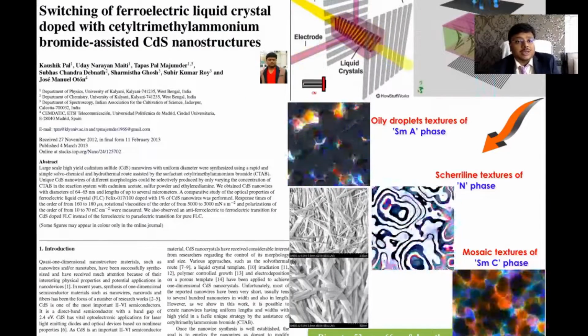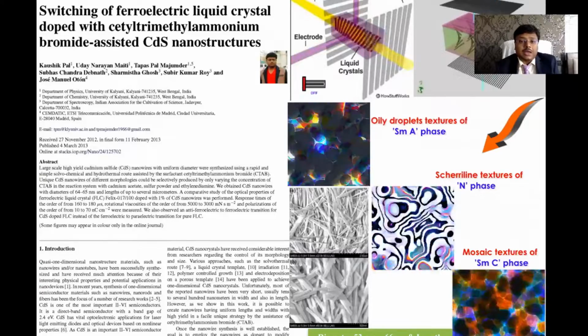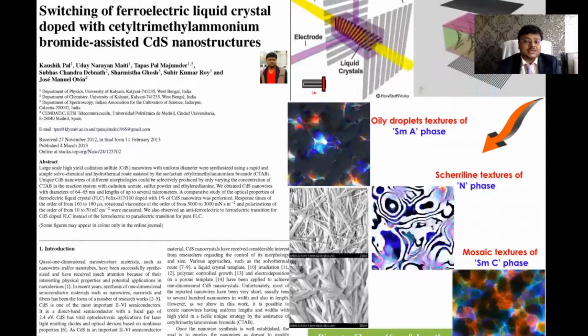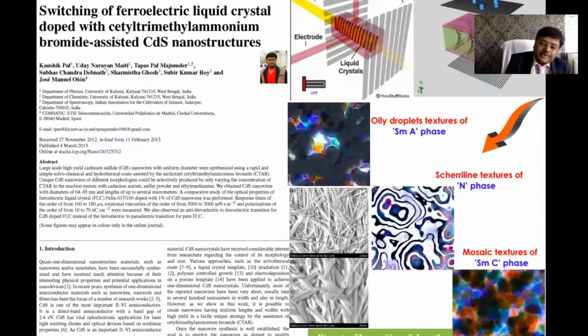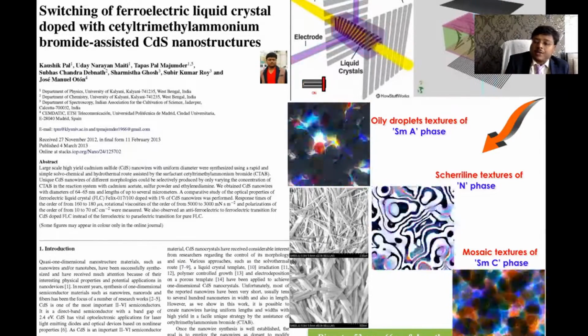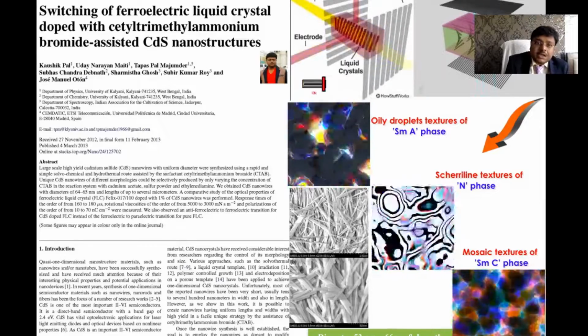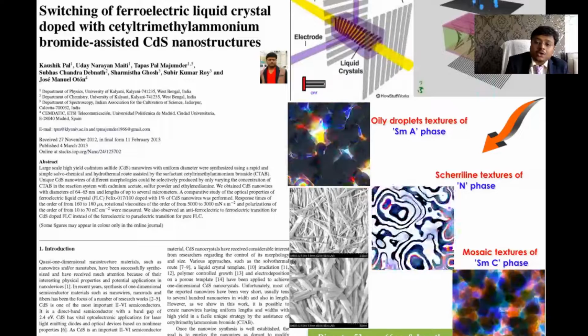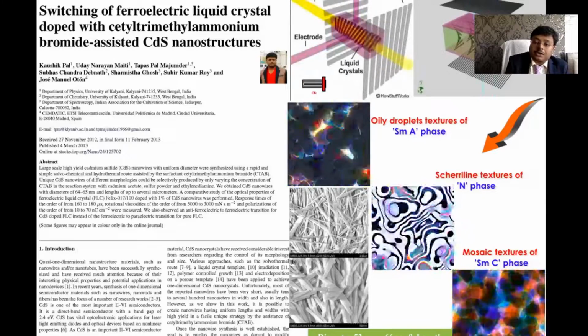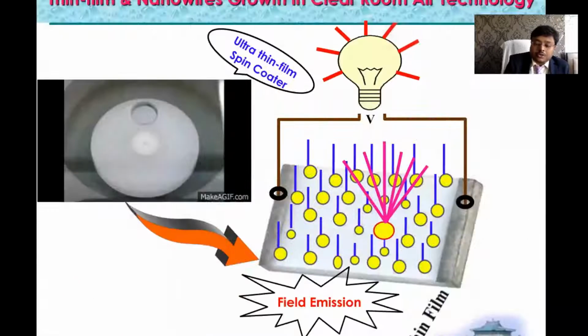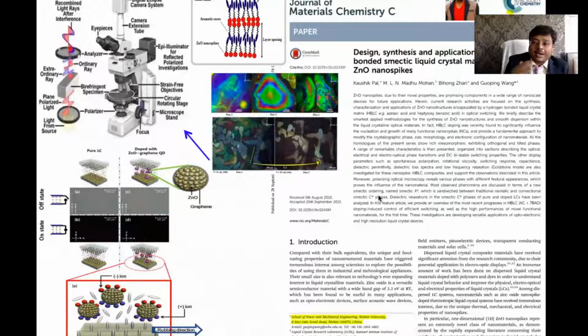Switching of ferroelectric liquid crystal dispersed with cetyltrimethylammonium bromide (CTAB) assisted CdS nanostructure. We introduced this material with a similar hydrothermal process, and made the deposition of liquid crystals into this ferroelectric liquid crystal. We also measured the characteristics with polarizing optical microscopy. You can see the oily droplet structure, shell line pattern, and mosaic structure, everything is formed. This is our polarizing optical microscopy. And this is our Chinese group working on this zinc oxide nanospike material with a smectic liquid crystal, and we published it in Journal of Materials Chemistry C.